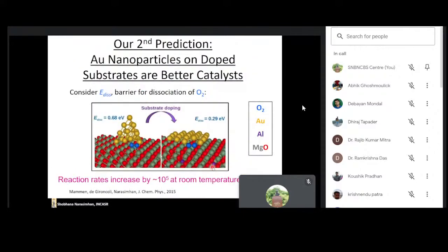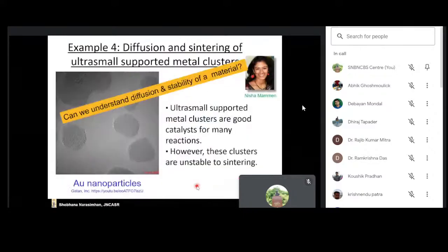And if we compute the dissociation barrier on the undoped support, where you have a three-dimensional nanoparticle, the dissociation barrier is 0.68 eV, whereas on the doped support, where you have the flat cluster, the barrier is significantly reduced to 0.29 eV. Now, if you assume that the prefactors are the same, etc., and you put in an exponential term, this would imply reaction rates were increased by about 5 orders of magnitude at room temperature. So it suggests that it indeed should be a better catalyst.